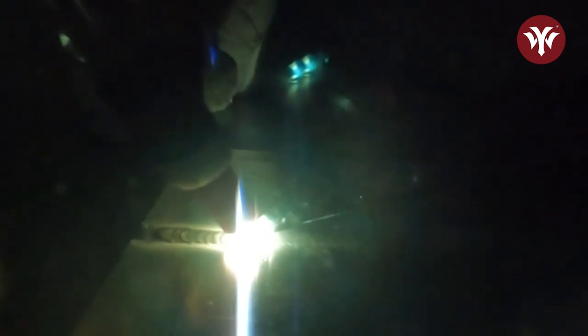Now we have a little bit of a keyhole happening. We're gonna go ahead, dab it in, and then move over a little bit. We're gonna let both sides melt in, keyhole, and dab it. And that is basically all we're gonna keep doing. You wanna watch that material flow in, and you're just adding enough filler to help the puddle. There we go. Move over about 1/8 of an inch, form a new puddle, dab some filler.